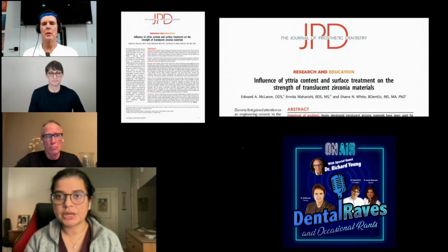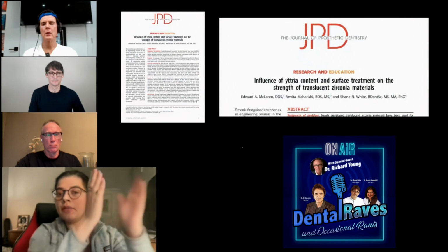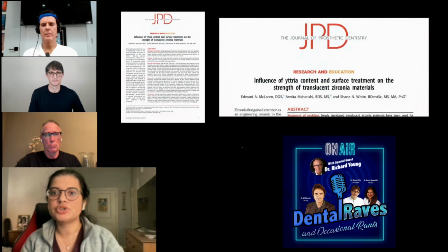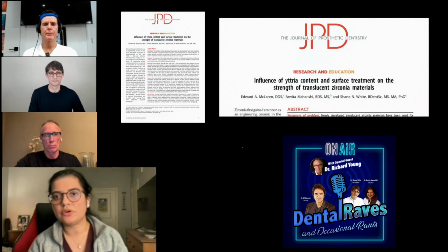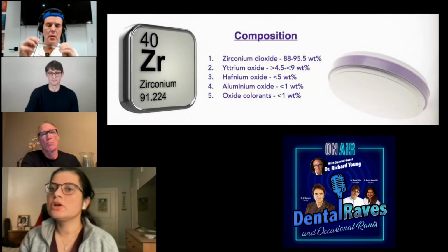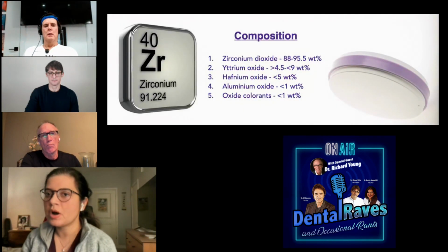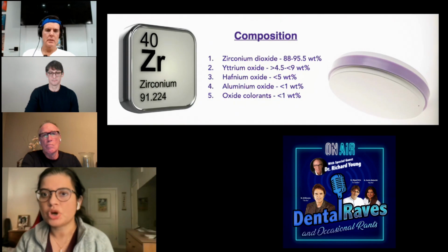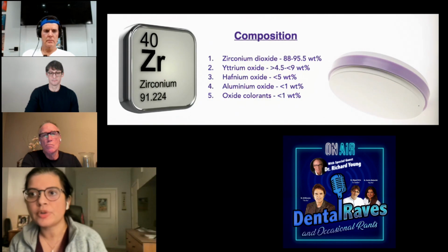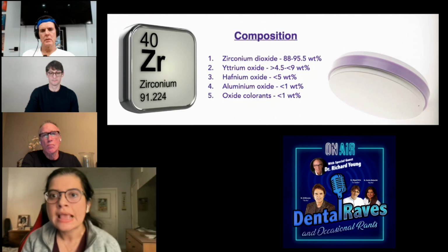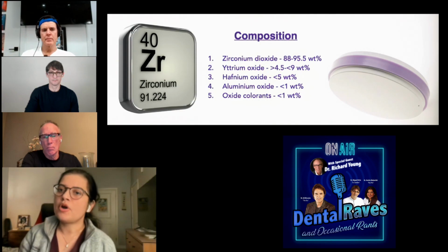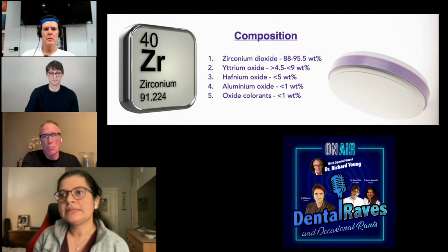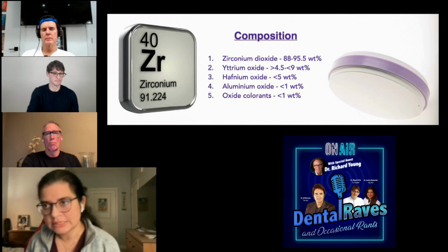For a day-to-day clinician, this is a very good education point, where I need to know whether I'm talking in the mole percent category or the weight percent category. Today we'll talk about the difference between weight percent of Yttria and mole percent of Yttria. This is the composition of zirconia slide, where yttrium oxide is the main dopant we are going to talk about today that affects the mechanical and optical properties of zirconia materials. Yttrium oxide in weight percentage can vary from around 4 to 9 weight percent, but it differs when we talk about the mole percentage.